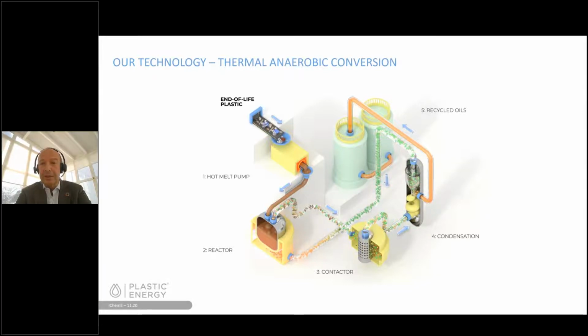Looking at how the technology works in a simplistic way, the plastic that we receive, we process it through an extruder, where we increase the temperature to 250 to 300 degrees, and then it goes directly to the reactor. In this reactor, we increase the temperature to about 450 to 500 degrees. Normally this is done with the synthetic gas produced in the process, in order to make the whole process energy neutral after the extruder. So that has been a big achievement in this type of technology.